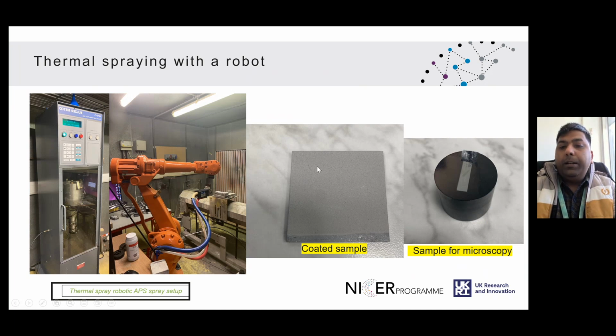And after the coating has been deposited, you can cut the sample to further mount it in the epoxy for doing further microscopy and further characterization. So that was done here. So after we have deposited the coating, we then performed the characterization, and these are very early stage results. We are still analyzing them, but in the hope of at least discussing through this particular communication video, I hope that we can have a thinking on what do we expect from such kind of studies.